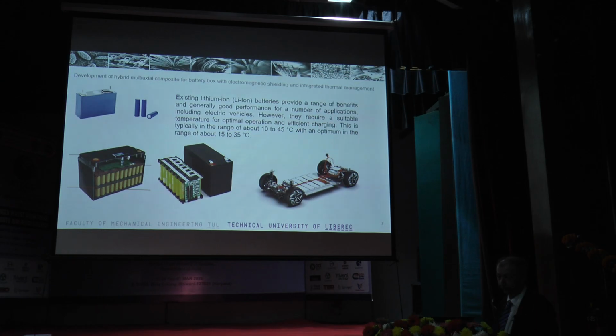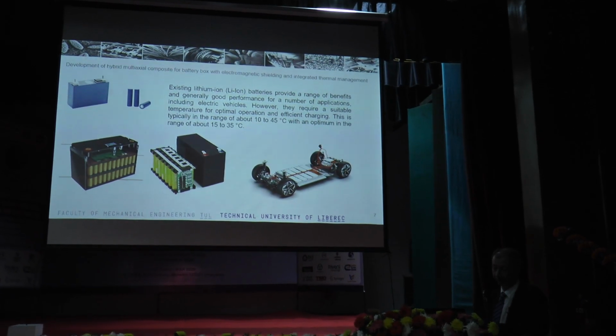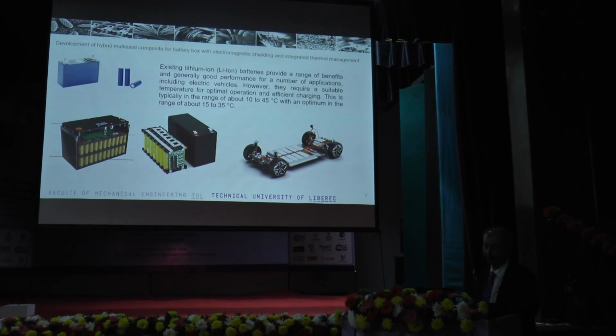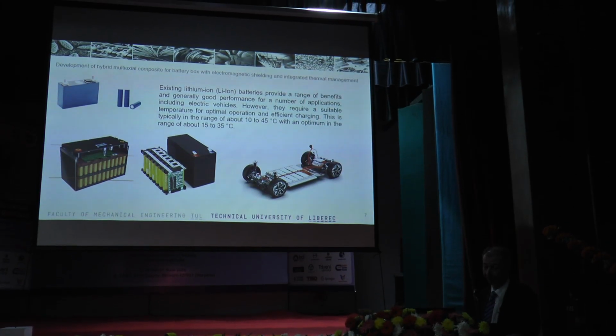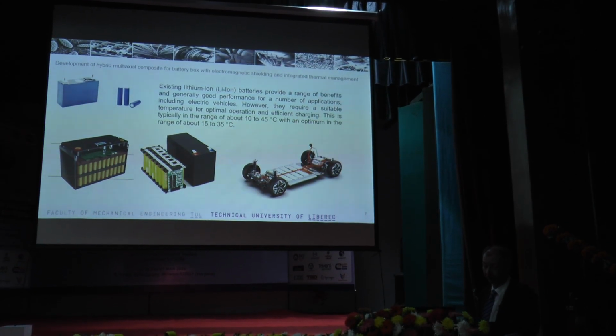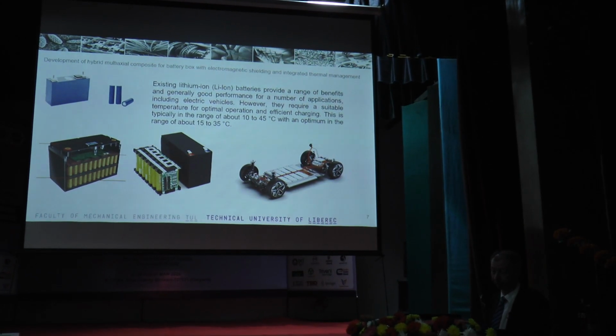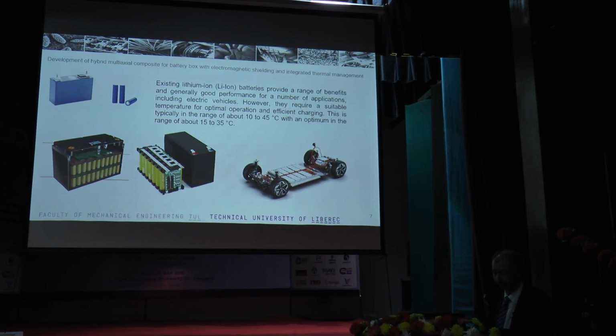A key parameter of the battery is temperature. Optimal temperature is about 15 to 35 degrees Celsius, but more interesting is the difference between individual cells. During charging, if the cell temperature difference is over 5 degrees, it can be a bit of a problem. If it's over 10 degrees, the lifetime of the battery goes down rapidly.